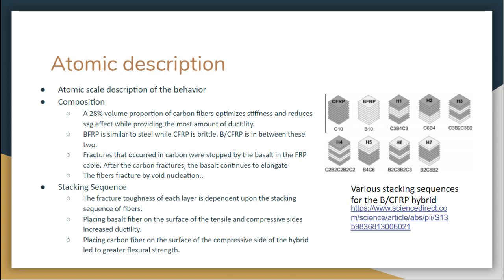This is due to the carbon fibers absorbing much of the load on that end because of carbon's higher tensile strength. When basalt fibers were placed on the tensile and compressive ends, we saw that the material had a high ductility and also low tensile strength due to the properties of basalt fiber. So from these observations, we can see that the stacking sequences play a major role, especially depending on the type of material on the outer surfaces of that stacking sequence.